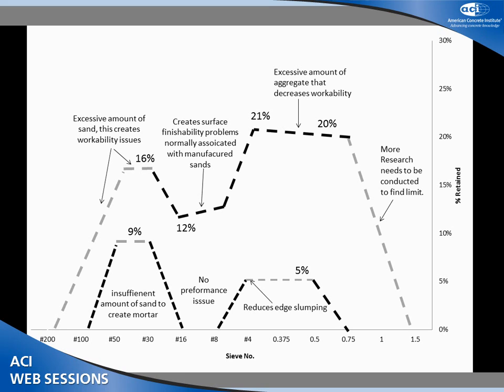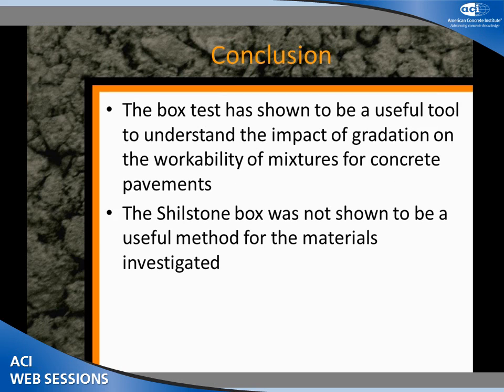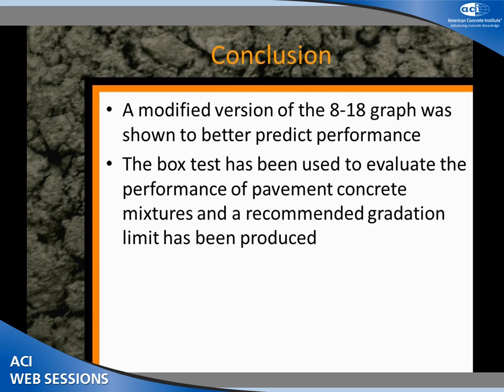This is cool and exciting. We've actually used this in the field — we've done 10 miles of CRCP pavement with this and it performed awesome. ODOT is actually looking to make this their optimized graded specification for the state of Oklahoma. In conclusion, the box test was shown to be a useful tool to help understand the impact of gradation on the workability of paving concrete mixtures. The Shilstone box was not shown to be a useful method by itself — you need to use it in combination if you use it at all.